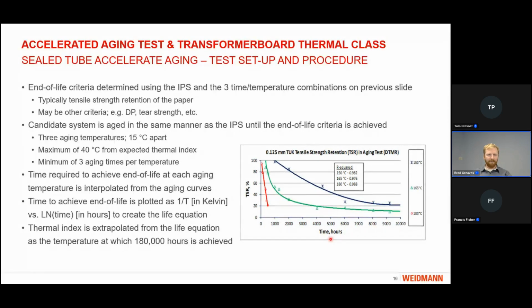Following that, once we have the time to end of life for all 3 aging temperatures, we plot those points in a life expectancy curve by plotting 1 over the temperature in Kelvin versus the natural log of the time in hours to create a life equation similar to what we saw from the IEEE standard. And using that life equation, we can extrapolate the thermal index of that insulation system, which is defined as the temperature at which 180,000 hours is achieved.